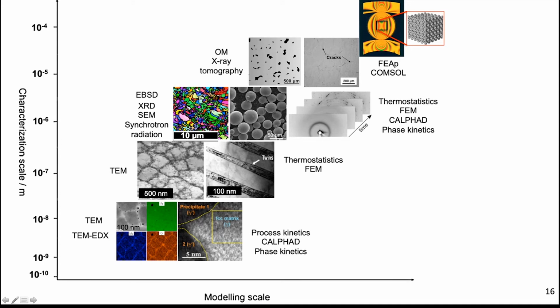And these are the characterization techniques. So as I mentioned, all these features and defects, the pores, the cracks, the fact that I print powders and their size, their grain orientation, the nanocells, there are techniques that cover across the scales all these features. They can all be observed. But matching each of these techniques, there is a modeling technique. So I can compute and prevent or control each of these features.